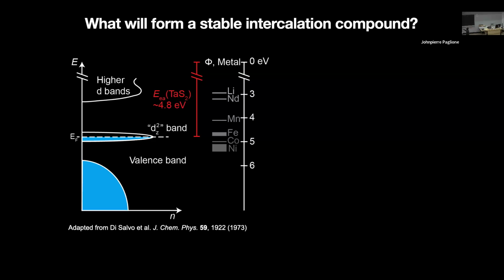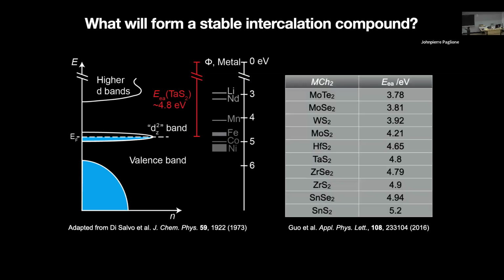And so it turns out that because first row transition metals by and large have work functions, let's say between 4 to 6, you really need host lattices with large electron affinities to get that reaction to happen. This is very different from, say, the intercalation of a lithium ion, like in battery chemistry, or even a rare earth. Those are very electropositive, and so they are very readily giving up electrons, and so you can intercalate lithium into, say, MoS2, or MoTe2, or MoSe2. Those have small electron affinities, but if you want to put a transition metal ion into a host lattice, you'll probably need to think about some of these ones down here with the larger electron affinities.